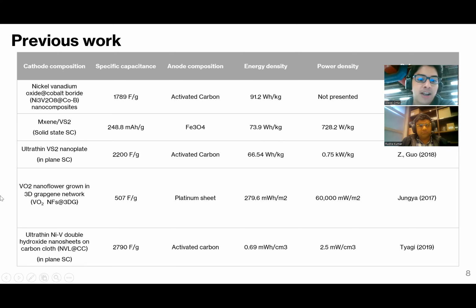So here, as you can note in this and in the other in-plane, which is the ultra thin nickel vanadium double hydroxide nanosheets, both of these have the highest specific capacitance of the ones here, getting the last one to almost 3,000. This is because of the specific surface being really high due to the specific microstructure, like in this project, really thin nanosheets.